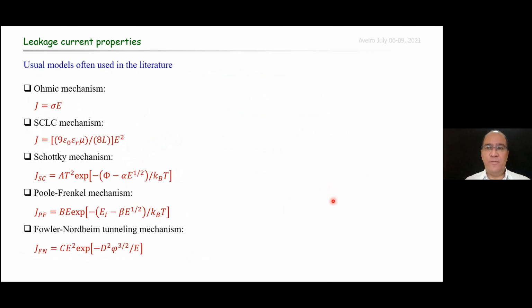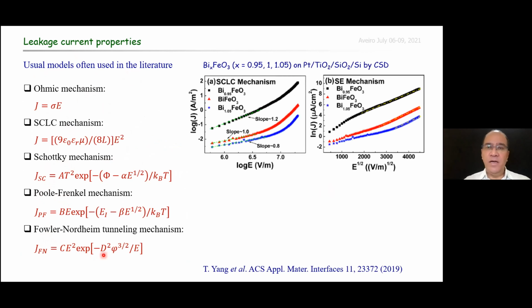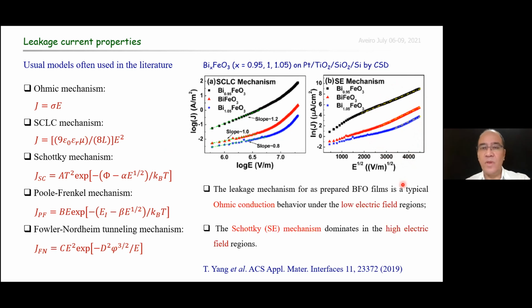Different mechanisms have been reported in the literature for the leakage current. The most common, the most used, are the ohmic, the space-charge limited conduction, Schottky, Poole-Frenkel, and Fowler-Nordheim mechanisms. Yang et al. concluded in their study that ohmic conduction occurs at low electric fields, while the Schottky mechanism dominates in the high electric field region, as summarized in this figure.